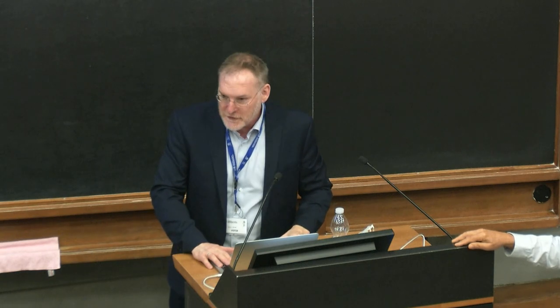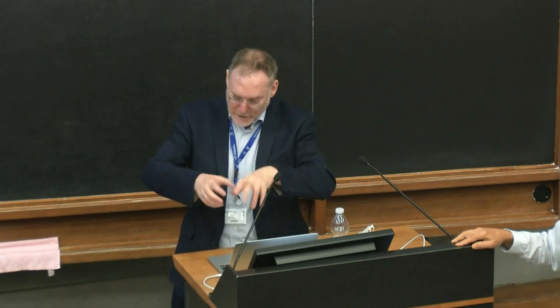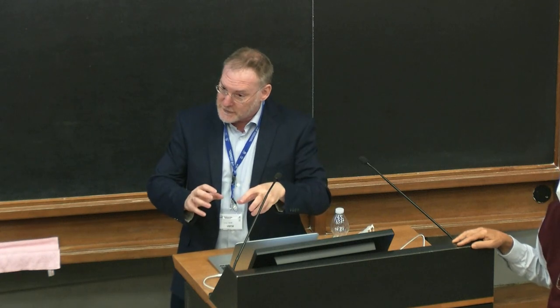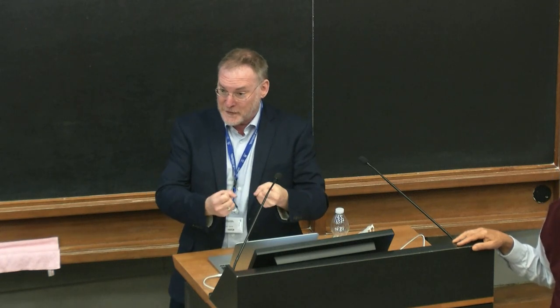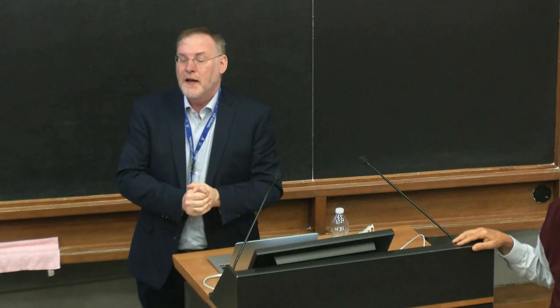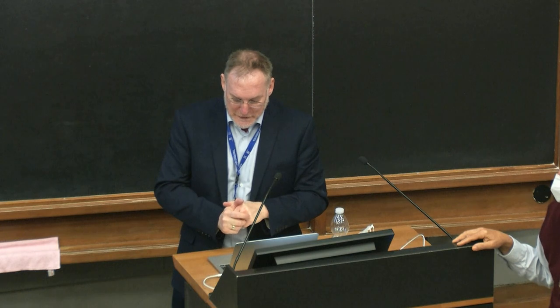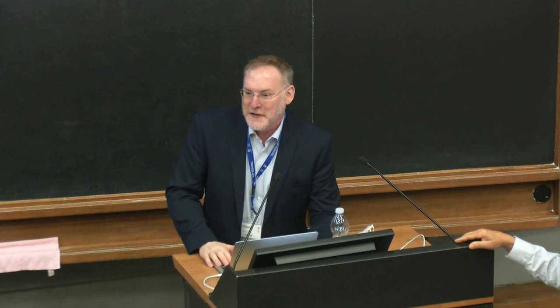We think that it's largely due to the quality of the contact. The thinner the graphene, the more flexible it is, the easier it is for it to find favorable interactions with the tip, and the friction goes up. But we think there's even more to the story than that. So from a friction standpoint, you need 4 layers.